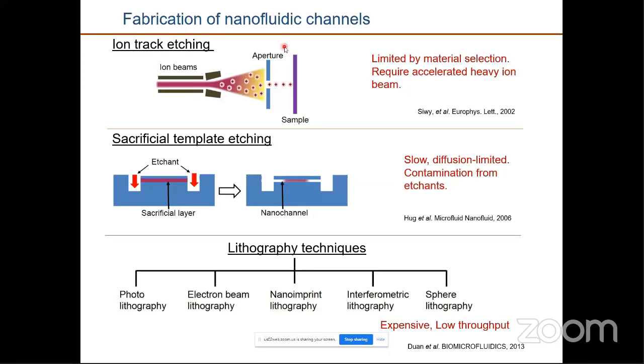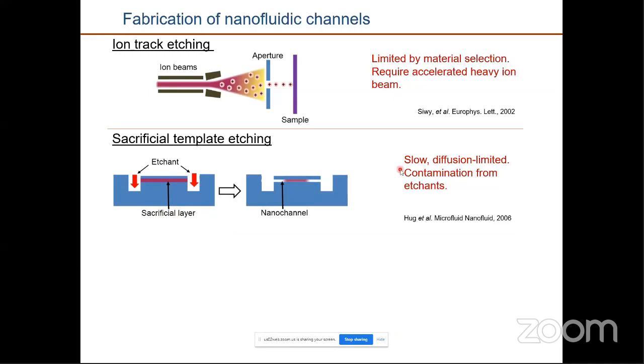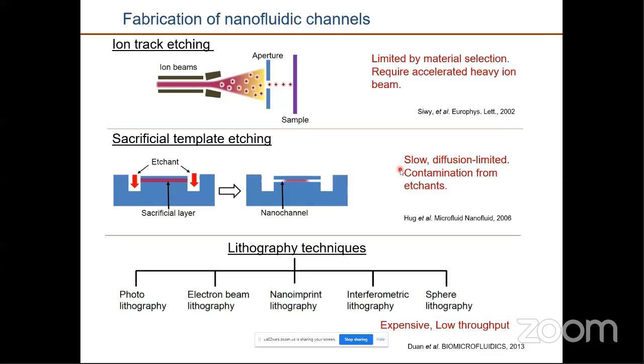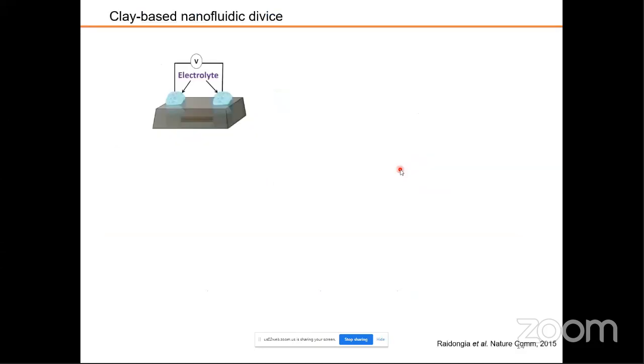All these techniques require very expensive instrumentation and are very time consuming, but we cannot make a channel as small as 1 nanometer. It is impossible using these techniques. On the other hand, in our technique, we can simply stack our clay sheets one upon another to make such small channels. Now, how do you confirm that we really made nanofluidic channels just by stacking clay layers?